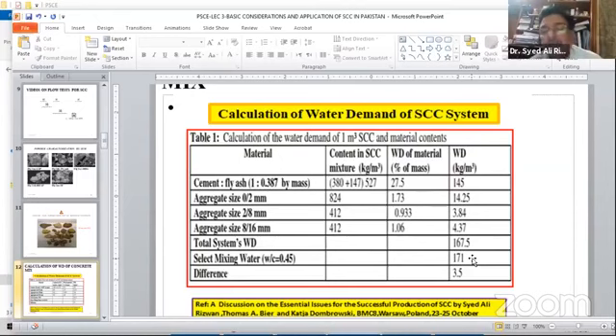Because I told you that the water demand and the mixing water content should be very close to each other. It should not be very far from the demand, should not be very less than the demand. Okay. So this is a very simple method. Although in Germany, one girl was known as Betonkönigin. It means the queen of concrete. She devised a special method to determine the water demand of concrete systems, and it was quite complex and not field oriented. So when I applied this method and compared with her results, the difference was only 1 to 2%. So you can do the Vicat test at the site. There is no problem.